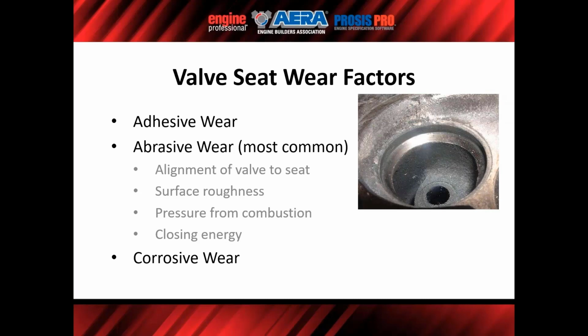So the pitting, again, can often be like the oxide, so it's a corrosion in more instances than not. So actually in here you see corrosive wear, but pitting is often corrosion. So something nasty in the environment of the combustion event. Is it fuel? Is it created by the timing process, so the burn's not efficient? Is it ingesting coolant? Is it the quality of the fuel in your area? But more often than not, the pitting is corrosion.